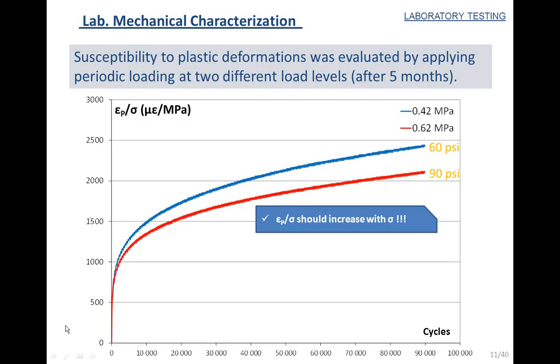So what you can see here is permanent deformation divided by the applied load. Here in the blue line we have divided the permanent deformation by 0.42, and here we have divided it by 0.62. So the thing is that this pattern was not expected, because according to plasticity, you should be expecting a higher ratio when the load increases. In practice, the typical result would be that the red line is over the blue line, because this is epsilon permanent deformation divided by the level of the load.